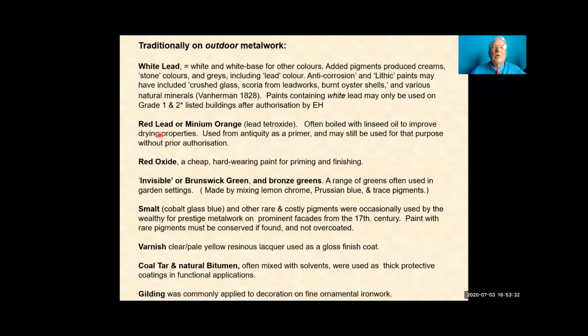Red lead or minium orange, that's lead tetroxide, is a bright orange color. That was a very good primer. Red oxide was a cheap, hard-wearing primer, commonly used. The expensive paints were often the invisible or Brunswick greens or the bronze greens, particularly if they used lemon chrome, Prussian blue, and the trace elements. They were quite expensive. Even more expensive was smalt, which is the cobalt glass blue.